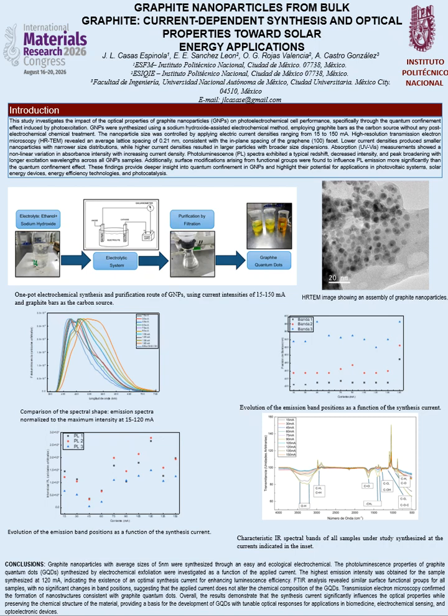HRTEM shows an individual nanoparticle from the sample prepared at 48 milliamperes, displaying average lattice fringe spacings of 0.336 nanometers obtained by fast Fourier transform analysis using digital micrograph software. This spacing is consistent with the interlayer spacing of a graphitic structure corresponding to the 002 crystallographic plane.